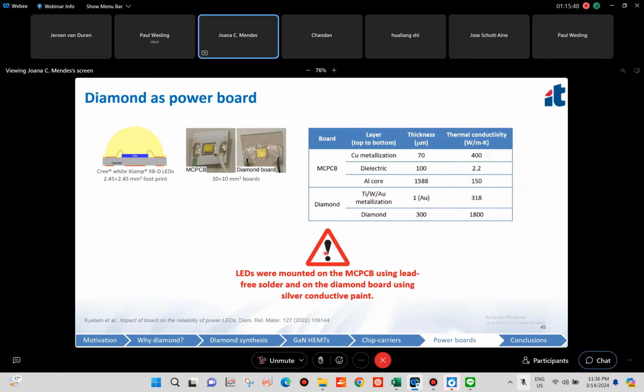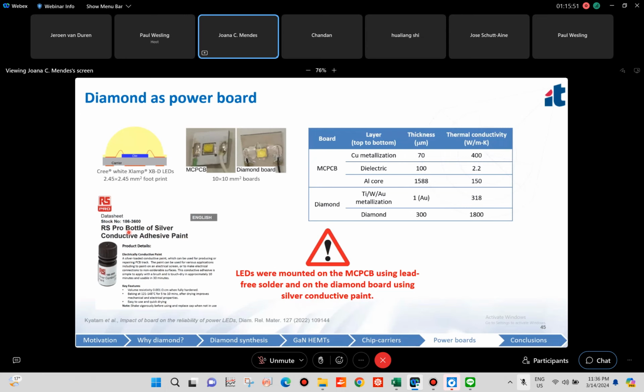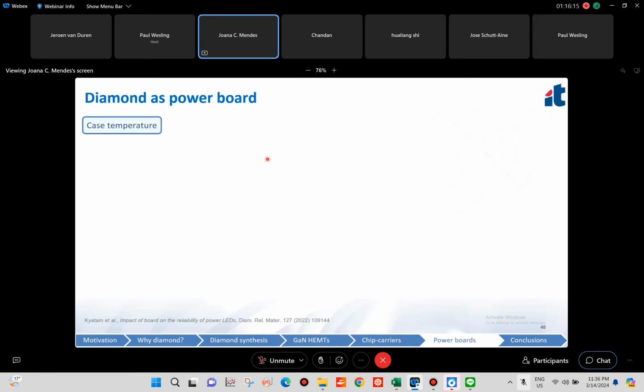So we decided to use silver conductive adhesive paint by RS Pro. And this will actually create some uncertainty, because you can see that the thermal resistance between the LED tracks and the MCPCB will be much higher than the thermal resistance between the LED tracks and the diamond board. But still, we proceeded to evaluate the evolution of the case temperature when we applied current steps.